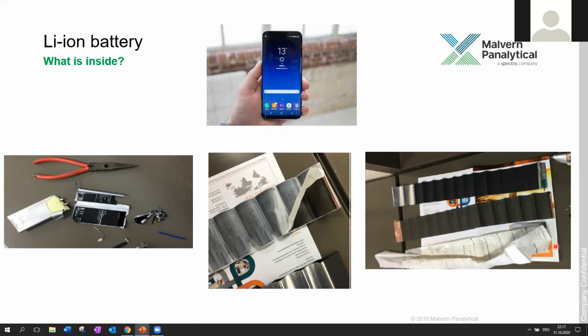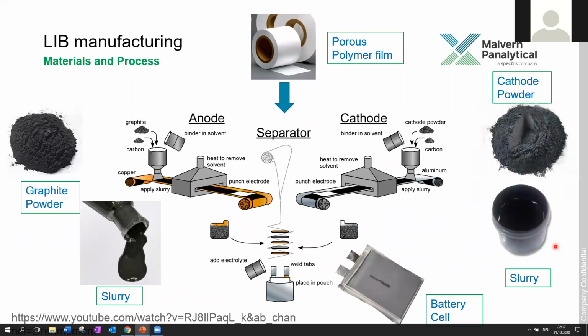Now, how can we manufacture lithium-ion batteries? Here's the process. We already know that we have an anode and a cathode. For the anode, we use this copper foil. We take graphite, carbon, and dissolve it. And from this graphite powder, we get a slurry. And then the slurry is coated on our copper foil. And on the other hand, the same with the cathode. You take your cathode powder, normally nickel, manganese, and cobalt, mix it with carbon and also a binder to generate the slurry, and coat your aluminum foil. And then you have to combine your coated copper foil with your coated aluminum foil and a separator and stack it together this way.